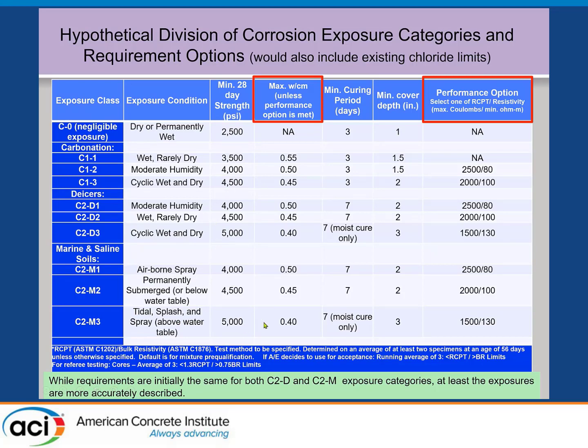We could have strengths and water cement ratios like now. And we could define curing requirements with increased amounts of curing required for different severity. The CSA code does that, for example. We could have increased cover requirements for these severe environments. These are just straw man numbers. I just threw them in the table. And instead of specifying maximum water cement ratio, and perhaps water cement ratio and strength, you could have a performance option. This is either to use the ASTM C1202 or the resistivity method, which is the ASTM C1876. And so there's two values there. That's the coulomb value, that's the resistivity value in ohm meters. And you have increasing requirements as the severity gets worse.